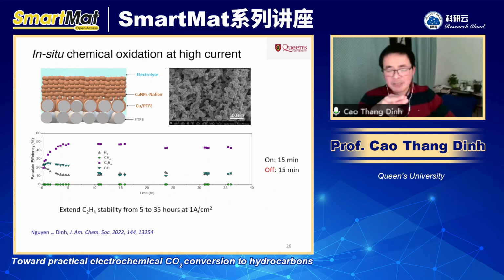So as you see here in this photo, after 35 hours of the reaction, you see a huge amount of salt here, which is potassium bicarbonate in this case. It has completely blocked the gas diffusion electrode. And when it is blocked, you do not have enough CO2, and then the system goes down. Other than the flooding problem, the salt problem is another problem in CO2 conversion, which is not easy to solve. And until now, this is still one of the challenges in CO2 conversion.